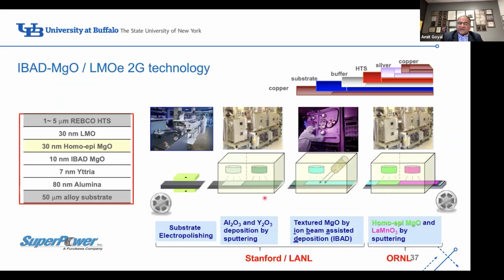The second process, LMO-enabled IBAD HTS wire. So here's a schematic of this. SuperPower is a company in upstate New York. You start with a very strong substrate like a Hastelloy. You first electropolish it, then you deposit some layers to planarize. Then comes the important layer, the ion beam assisted MgO layer, just a few tens of nanometers, 10 nanometers, and you can get the orientation you need.